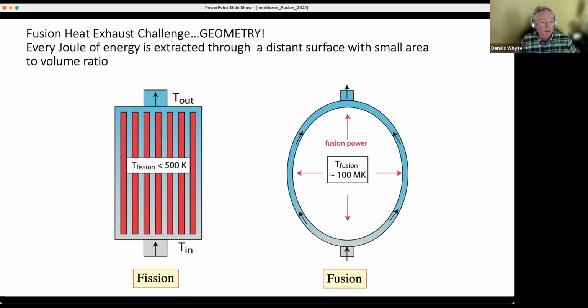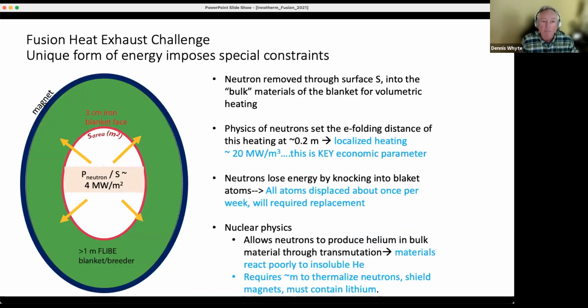It's because all of the heat is generated in a single volume that literally cannot touch anything. So every single joule of energy that's produced by this 100 million degree plasma, however you're going to get it out, has to come out through a single surface. And that single surface is going to be surrounding the plasma. So this already geometry disfavors you, in some sense because of the requirement of confinement of the plasma itself.